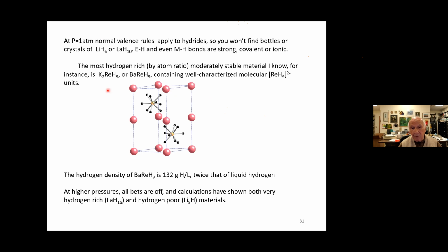For instance, I don't think many people knew that you can get, here's the most hydrogen-rich compound at 1 atmosphere. It's barium-rhenium H9. I've defined hydrogen-rich here by atomic ratio, not by mole ratio, not by weight ratio in any kind. So there are 9 hydrogens. Normal valences, barium rhenium H9 has a ReH9 2- ion, which if you like has 9 H minuses, a rhenium +7. Rhenium is under manganese in the periodic table. That's a 2- ion, ReH9 2-. And we actually know the hydrogen positions from a neutron structure, and there is a barium 2+ to balance it.